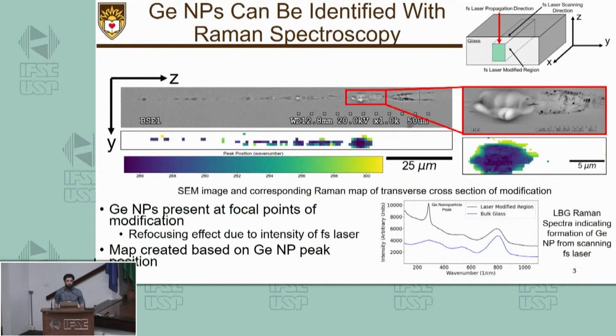So trying to identify germanium nanoparticles in my glass is rather difficult because my modifications are so small, but we're able to use Raman spectroscopy to identify the relative location of the nanoparticles. And we'll have a distinct peak that forms in the glass that we use to create the different maps.